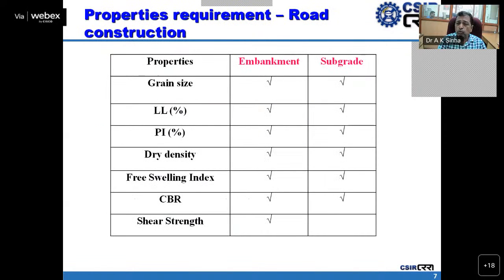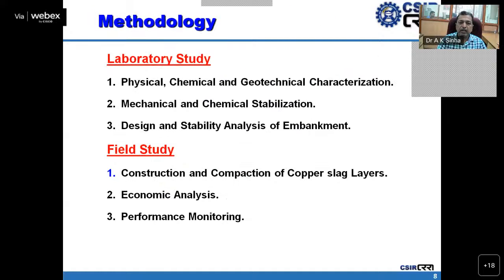So pertaining to road construction materials, in application of embankment or subgrade, these properties were determined: grain size, liquid limit, plasticity index, dry density, free swelling index, CBR, and shear strength parameters, for embankment and subgrade application. The whole methodology was bifurcated into two stages, laboratory studies and field studies.